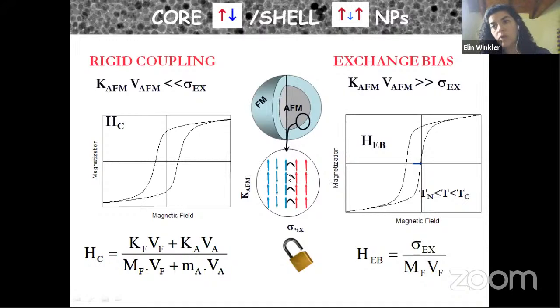So in that case, we will find a preferential orientation when the magnetic field is along one direction. For example, in this case, the energy is lower when at the interface, the spins of the antiferromagnetic and ferromagnetic are parallel. So if we want to invert, we have to exert an extra torque in the opposite direction to invert the ferromagnetic phase. So in this situation, how can we observe that exchange energy? Well, we observe an asymmetry in the hysteresis loop. We observe that the center of the hysteresis loop is shifted, and this field, which is called the exchange bias field, is proportional to the exchange interaction at the interface.